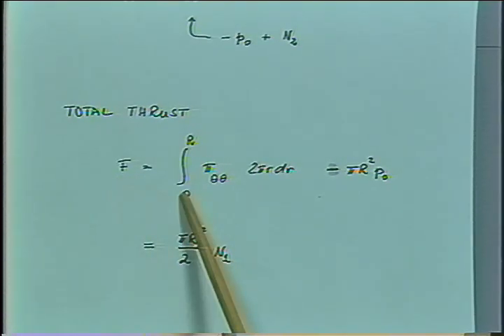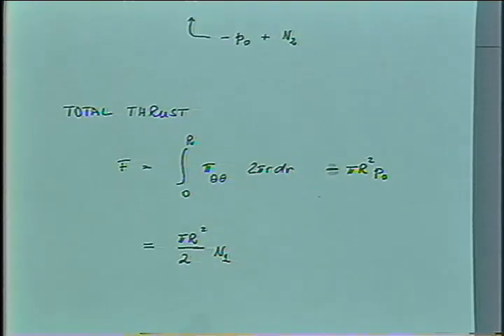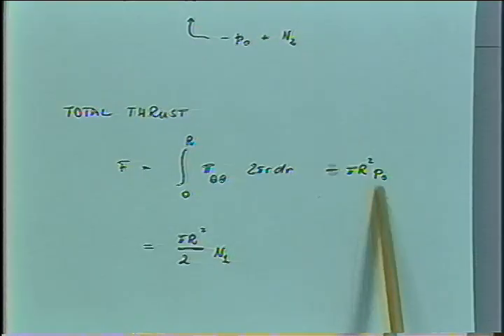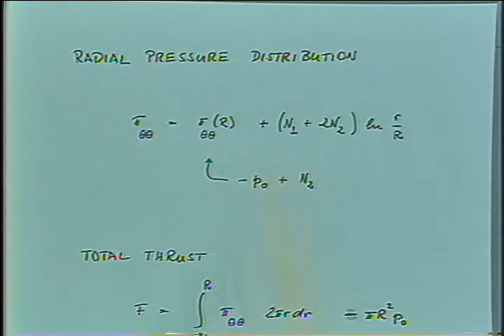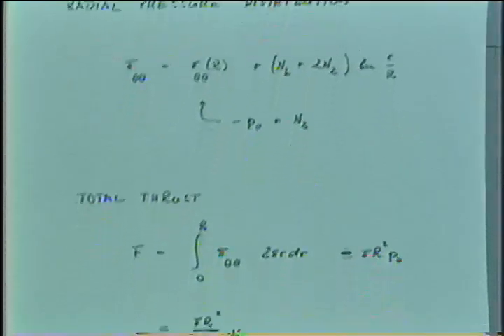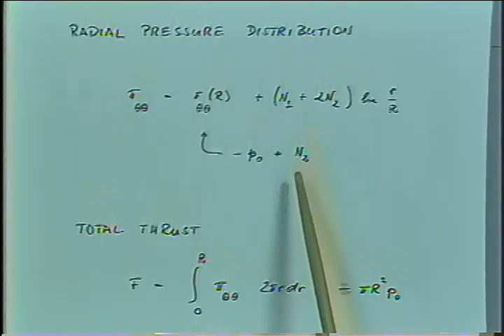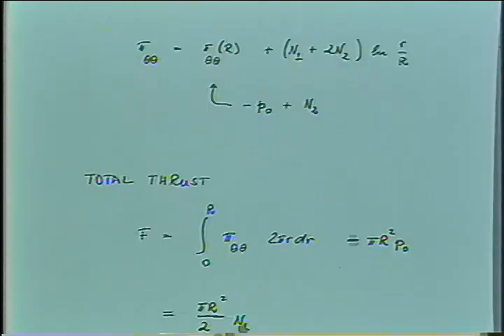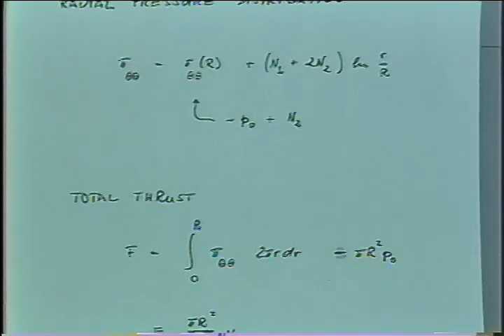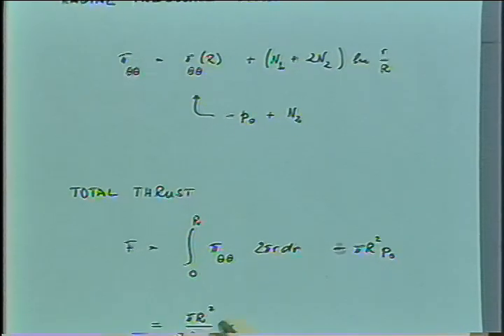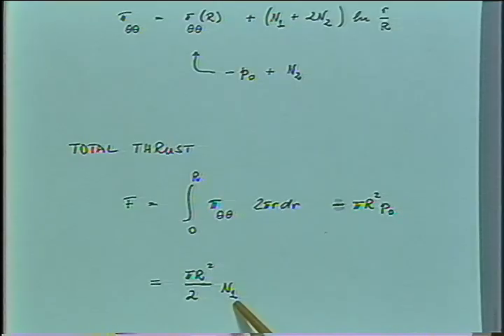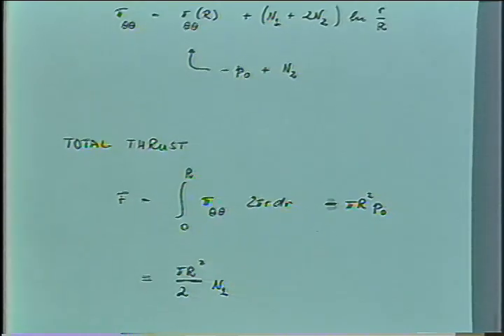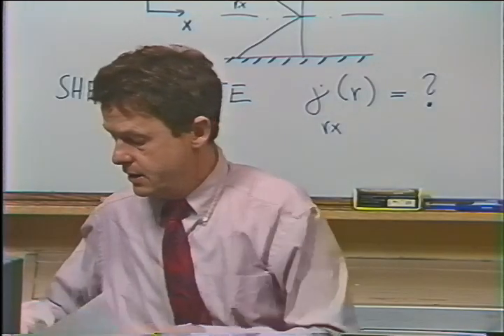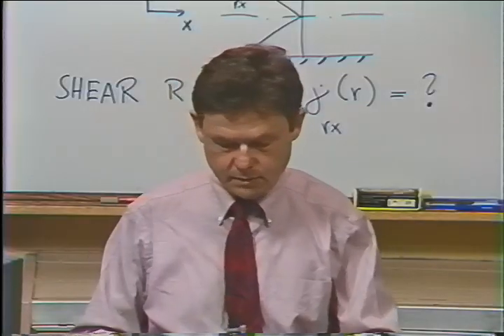The thrust is given by the integral over the surface area, the stress over the surface area. We have to subtract the atmospheric pressure because the atmospheric pressure came also in here with a free surface. So this has to be a minus sign. And then some terms cancel. All the terms which contain N2 are canceling in here. And you will find that the separating force is just given by the first normal stress difference at the shear rate at which we do our experiment, multiplied with a geometry factor. So it's a very nice, very straightforward analysis which helps us understand the system.